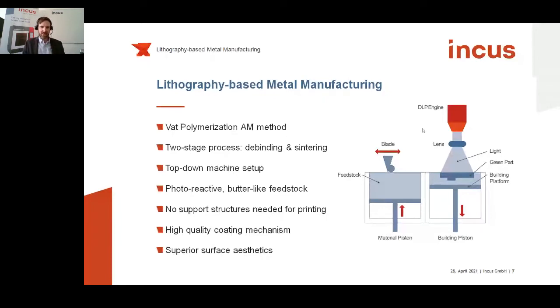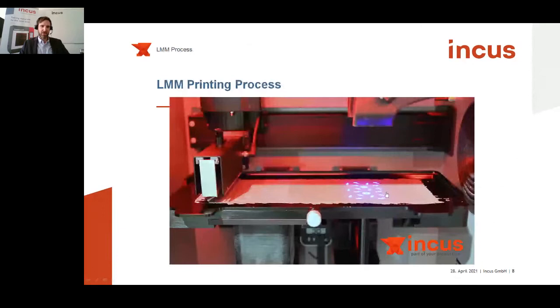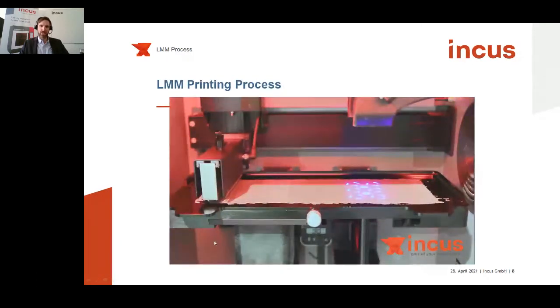The special thing, or the secret sauce for us, is the photoreactive butter-like feedstock. At room temperature, our feedstock, the raw material, is solid, and at coating temperature around 30-40 degrees Celsius, it turns liquid. So we always coat a liquid layer of material on a solid surface, and that allows us, together with the high quality DLP or projector unit, to create parts in the highest possible surface aesthetics and accuracy for metal additive manufacturing. So what's also indicated in this scheme on the right side is that we don't need supporting structures to connect the parts to the building platform, and we can print overhang structures, also without any connection to the building platform. I have a short video, I hope it runs smoothly for everybody, showing the printing process.